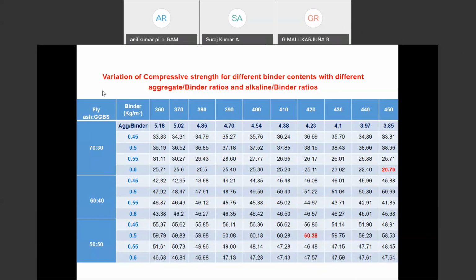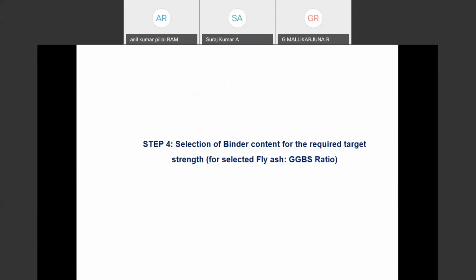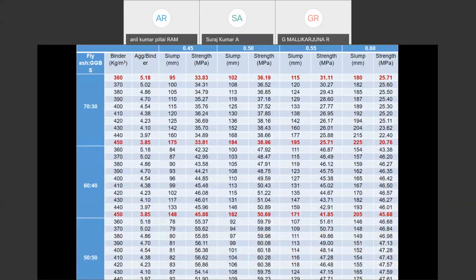So that we get the required strength, again we have selected two values. One is for 450 kg per meter cube, we have considered 20 MPa, and for 420 kg per meter cube we have considered 60 MPa strength for trial. And after that, these are the charts we have developed for the total geopolymer.